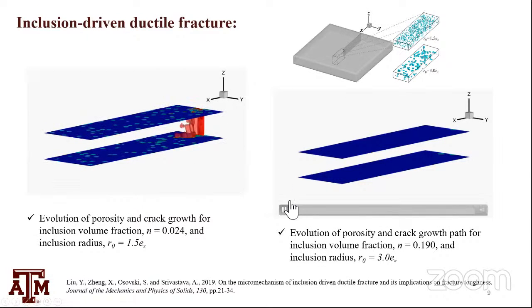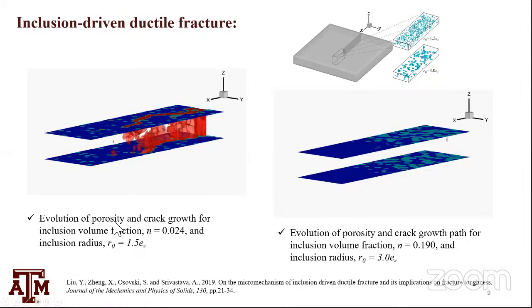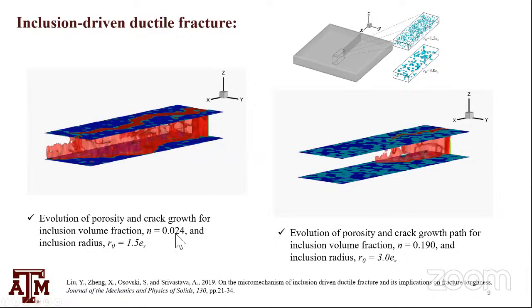We could do this for different inclusion sizes. This is double the size of the initial size. EX is the mesh size. I have a volume fraction of 19%, around 0.19, a pretty large volume fraction. And we can simulate these three-dimensional crack growth paths.